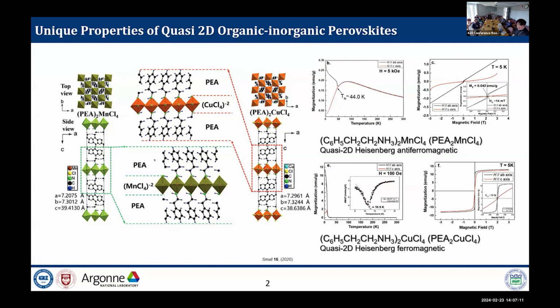In the copper-based material, PEA2 copper tetrachloride has a copper tetrachloride octahedral structure layer like this. Between the copper tetrachloride layers, there are organic PEA cations. So the metal halide octahedral layer is separated by the PEA cation, and because of the excessively long length of the PEA molecule, there is a long gap between the layers, almost 2 nanometers. So the layers are almost independent, and this is why the material has a quasi two-dimensional structure and properties. Similarly, PEA2 manganese tetrachloride also has manganese tetrachloride octahedral layers between the PEA cations, with almost the same structure as PEA2 copper tetrachloride. This quasi two-dimensional structure stands out in its magnetic property because the origin of the magnetic moment is the metal ion.